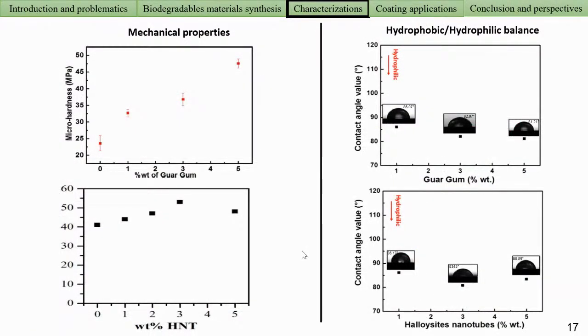The aim of this study is to improve the mechanical properties, and we can see from the microhardness that we improved the mechanical properties, even with guar-gum or halloysite nanotubes. Also, the balance between hydrophobic and hydrophilic character is a crucial parameter for coating fertilizer and also for food packaging. So we studied the contact angle of our nanocomposite, and we observed that the contact angle decreased by increasing the content of the filler. This indicates that we can tailor our materials to be more hydrophobic or more hydrophilic just by varying the ratio of the fillers.